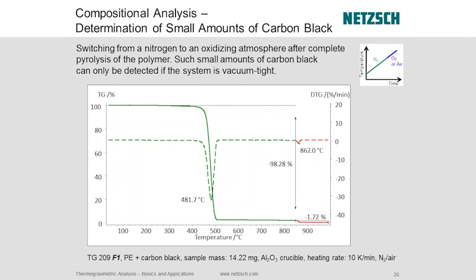Okay? So if you had outside gases, air, mixing into your nitrogen purge, for example, that carbon black would probably get consumed somewhere here along the process, and you wouldn't be able to characterize it. So using a vacuum tight instrument like NETZSCH offers, you can very, very cleanly separate something like carbon black from the polymer backbone. Okay, so that's a very important comment. Otherwise, if we ran the whole thing under air, it would probably look like one big blob. Or if we ran it under nitrogen and there was oxygen leaking in, again, it would kind of all smear and you wouldn't really get this nice perfect mass loss step for the carbon black. Okay, so please remember that. Vacuum tight.